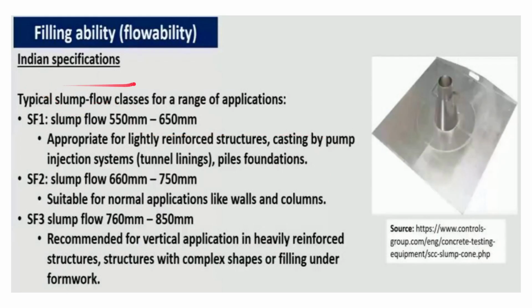Now according to the Indian specifications, the slump flow can be categorized into various categories, which are used for various ranges of applications. If we require a flow appropriate for lightly reinforced structures, like casting by pump injection systems, tunnel linings, piles, foundations, we can reduce the flow to 550 to 650 mm, which is category SF1. For normal applications like walls and columns, we can increase the slump value a little, from 660 to 750 mm, say,